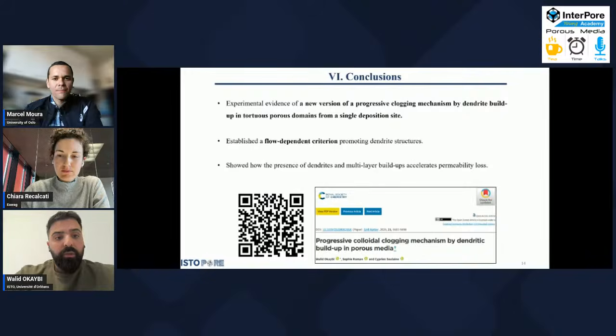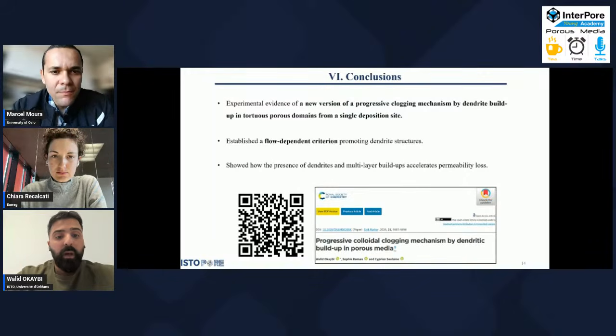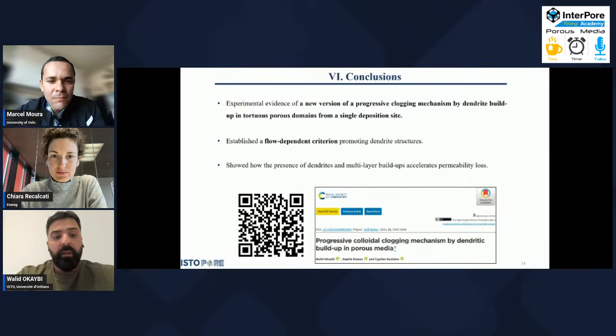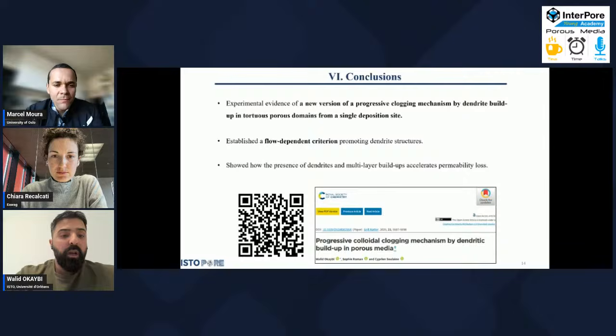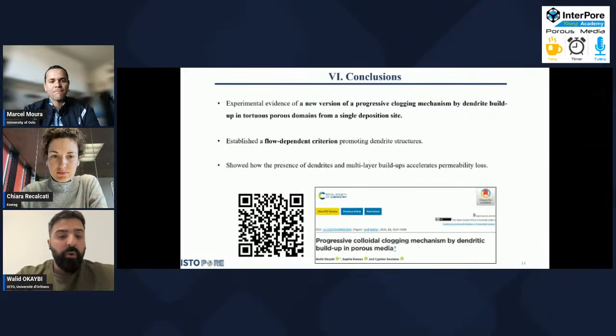So as a conclusion, we have provided experimental evidence of a new version of progressive clogging mechanism by dendritic buildup in tortuous porous domains, however, from a single deposition site. We established a flow-dependent criterion which promotes the dendritic structures, and we showed how the presence of dendrites and multilayer buildups can accelerate permeability loss in the system. And for more information, you can check our published paper in Soft Matter, Journal of Soft Matter.